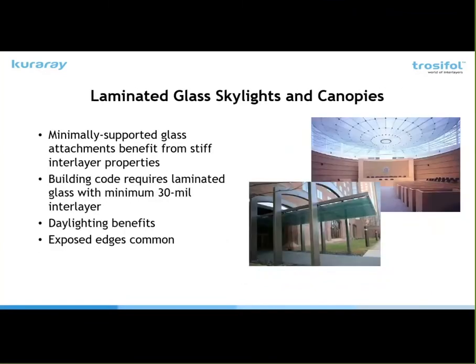As far as overhead is concerned, the codes call for a minimum 30 mil PVB interlayer. And the key word there is minimum, because in a lot of cases, when it's engineered, it won't meet the requirements. So in these two pictures here, you see large point-supported glass. That's in Phoenix. So with the heat, you may get some sagging, and you'd have to go thicker with the glass if you didn't have a stiff SentryGlass type interlayer. This is a good example where you have exposed edges and point support, and you'll see in the next chart and video what happens when you have that type of situation.